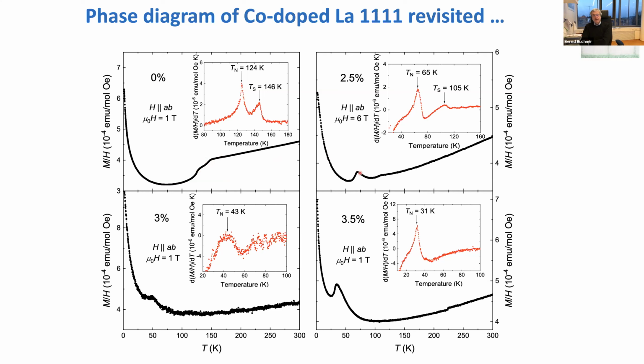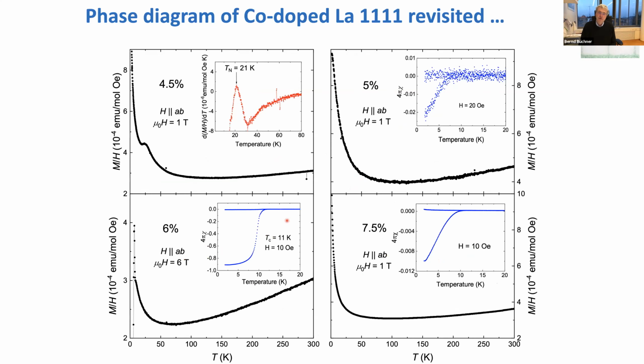Surprisingly, the magnetic transition becomes sharper, very nicely visible. It's probably telling us something, but it at least gives you a chance to measure the phase diagram. If you go to higher doping, the systems become reasonably good superconductors. At optimal doping, Tc is small, but this is known because cobalt impurities reduce Tc. But it's also clear that magnetism disappears at about 4.5%. Superconductivity is very strong at 6%, and in between we have, let's say, very weak superconductivity and no magnetic order.